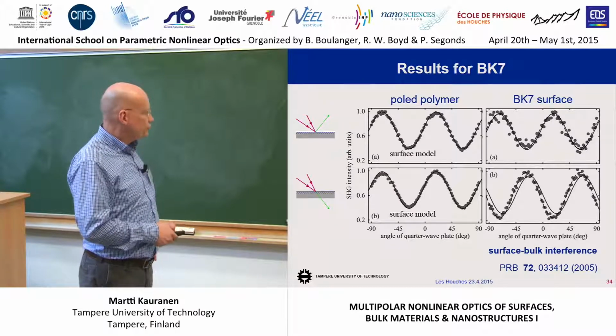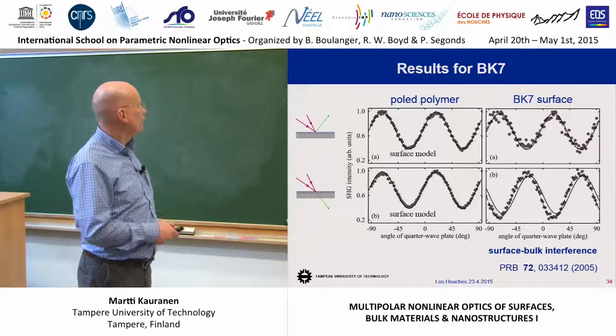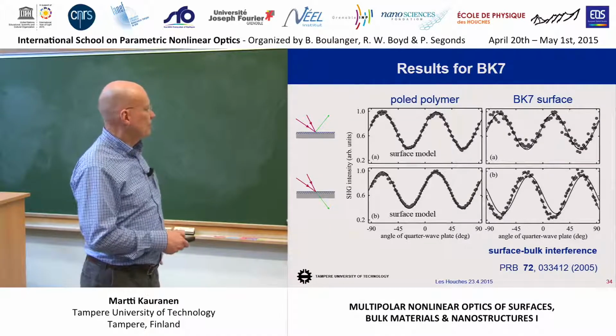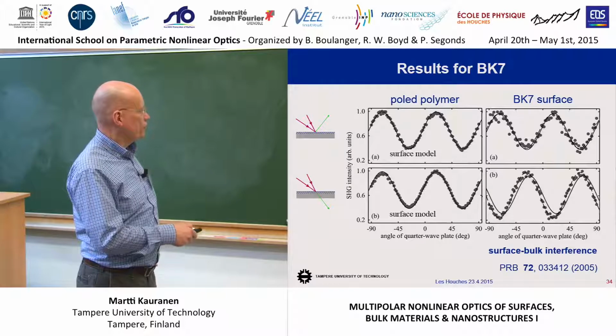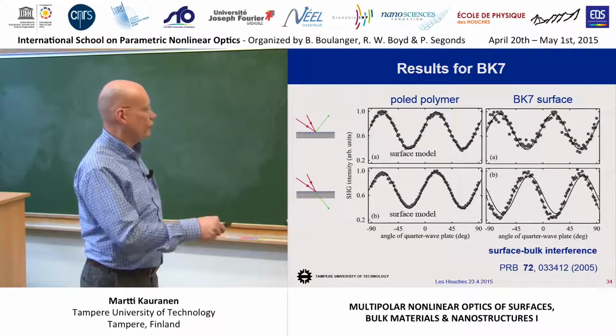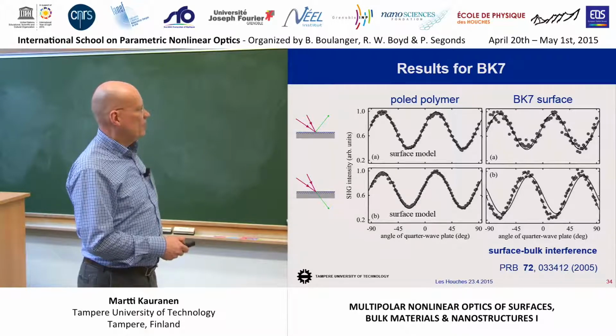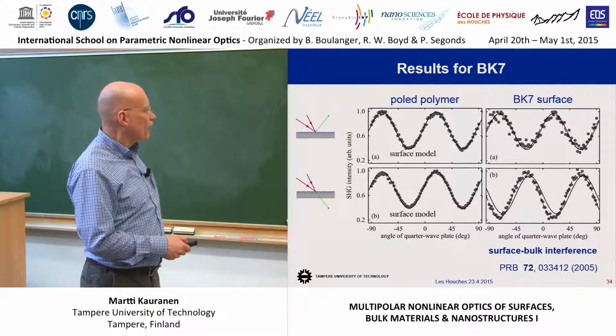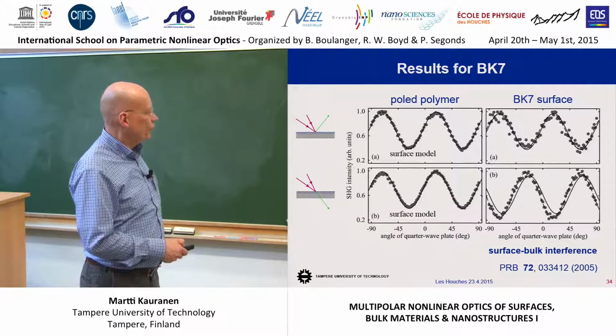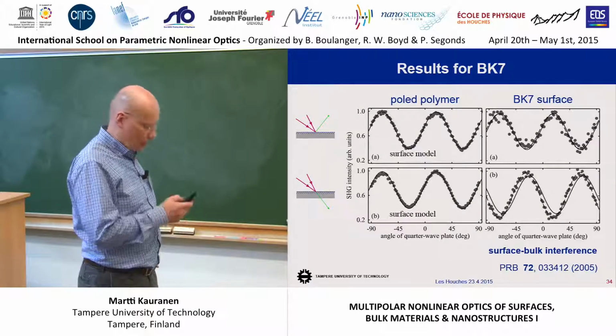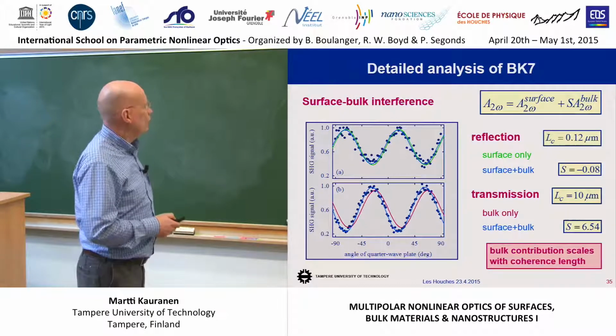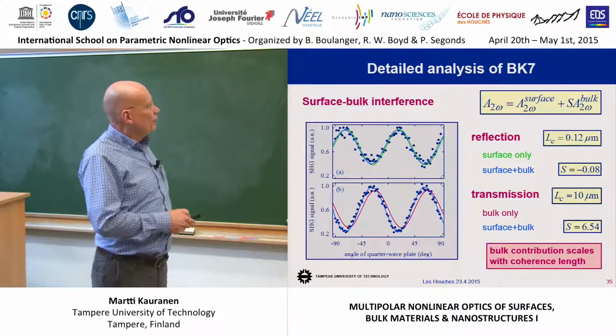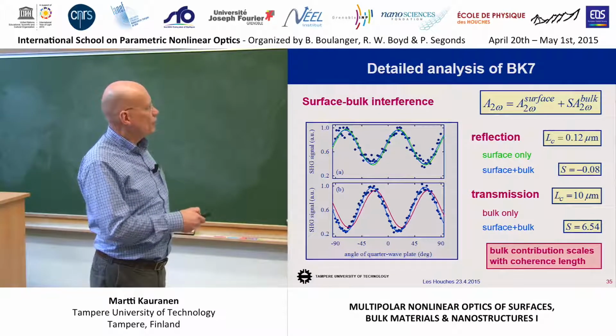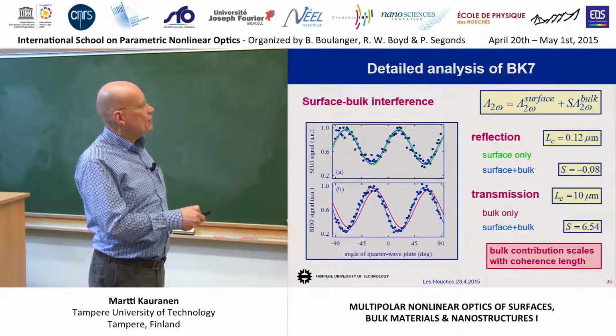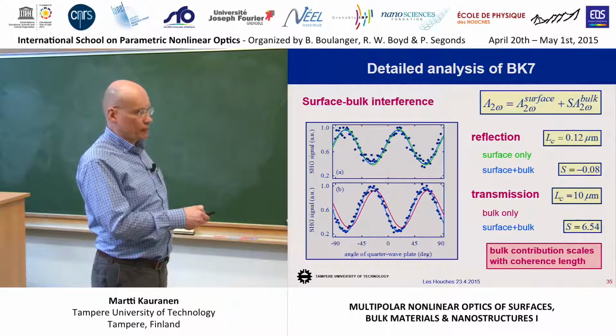And then for the transmitted signal, we are not even close to this surface model. This is the way it should behave, and we're sort of out of phase completely. And we get a much better fit using the bulk model, but it's not perfect. We can improve the fit by taking into account the interference between the surface and bulk responses. Okay? And then furthermore, when we look at the data more carefully, we can fit the data to this model. We have the surface response plus some coefficient times the bulk response.